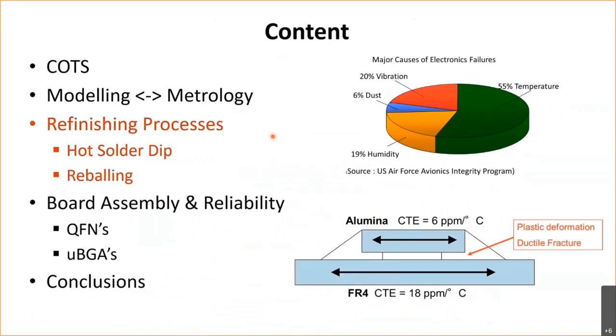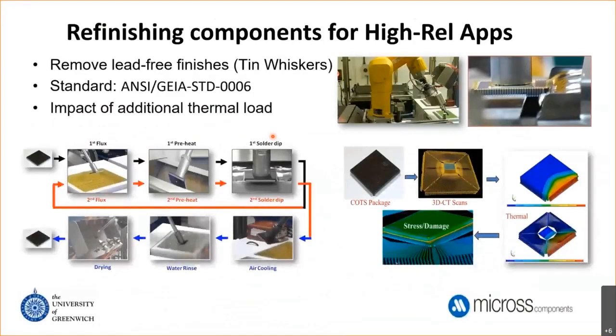Okay, refinishing processes. So let me start with this process. So here, a component, this is a leaded component I'm illustrating here, but this hot solder dip process, robotically controlled, essentially the leads of this component need to be dipped into a solder bath to make those leads compliant with the application for an aerospace application. The primary concern here, one of the primary concerns, is tin whiskers. So here we can see the actual robot arm system, the fluxing, preheat, solder dipping, air cooling, water rinse and drying. And you've seen this picture before, but again, the leads being inserted into a solder bath.